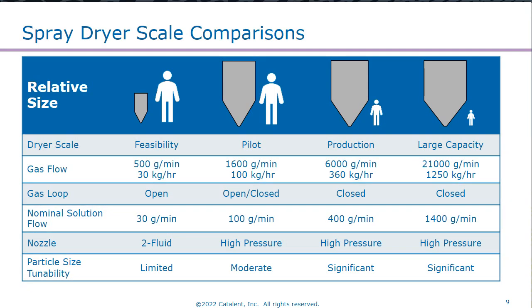Throughout this, I think it's helpful to have an understanding of the scale of dryers we're looking at. Early feasibility studies are often done with rather small dryers. These are your Büchis or your ProCepts. The gas flow is slow, and they're typically run in open loop, which means we don't recycle the nitrogen during spray drying. We have drier processes overall. These are also done with two fluid nozzles, where we have limited particle size tunability. You'll often have very fine particles, and you need to be careful to ensure those are dry before they impact